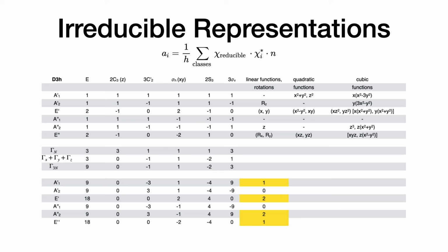So you see that you can write that in a form that's more conventional. We have a direct sum. And by the way, I should have used this direct sum with a circle around plus on the previous slide as well, but that was implicit. But the gamma 3n, so the representation of the displacement, which are related to phonons, is actually pretty rich. We have A1 prime, 2E prime, 2A2 prime prime, and E prime prime.